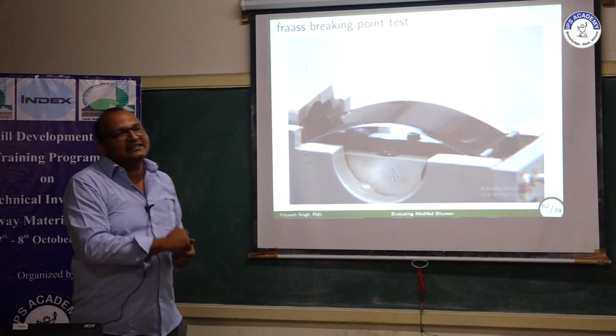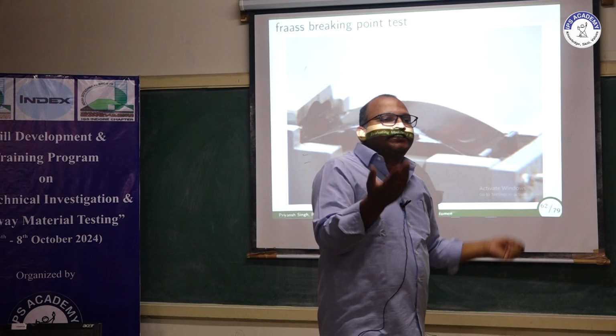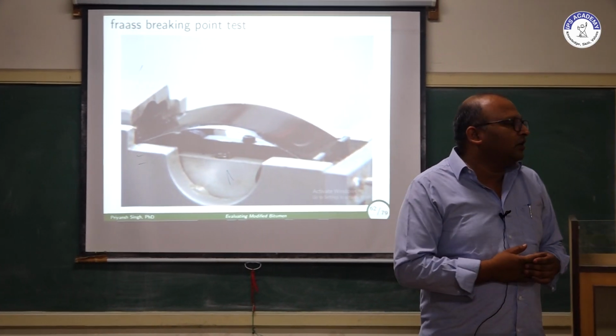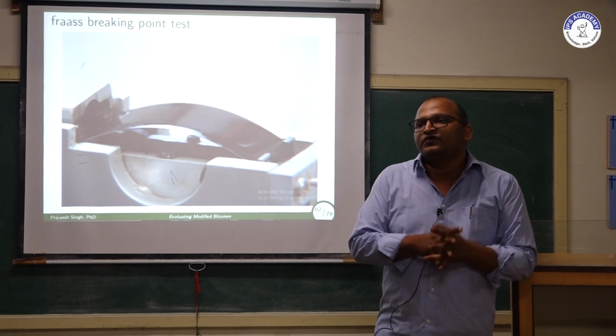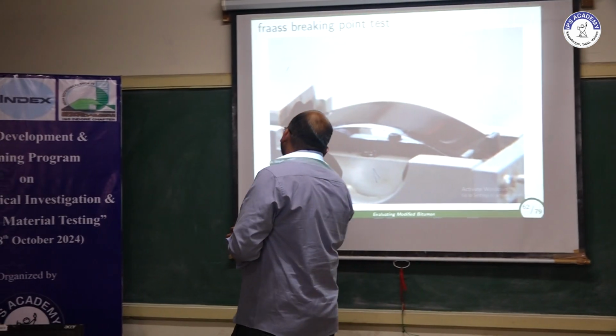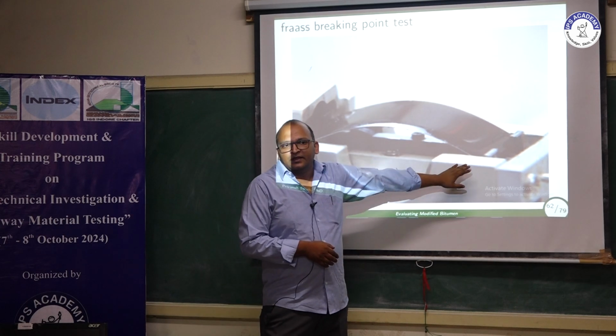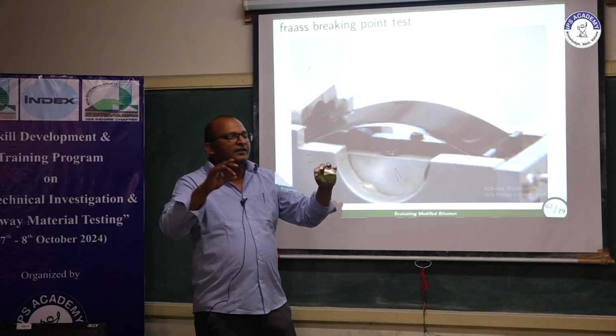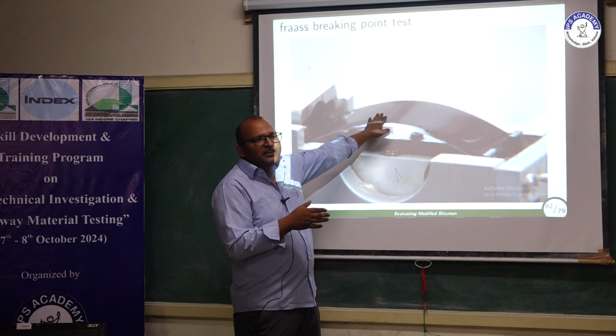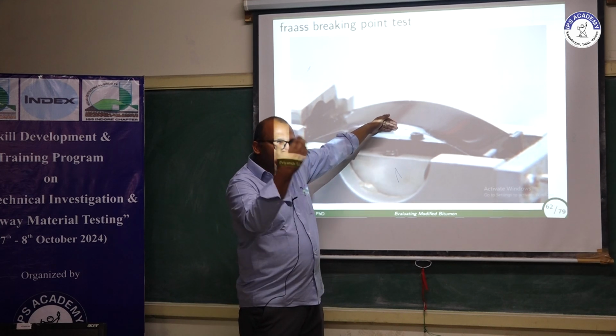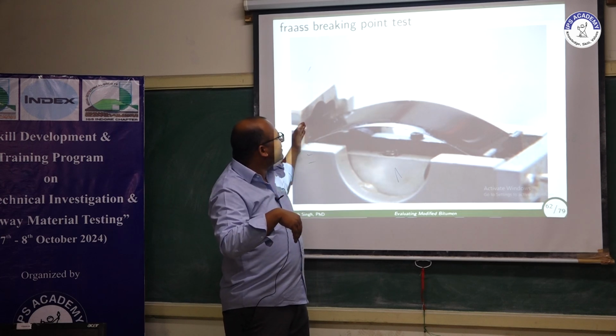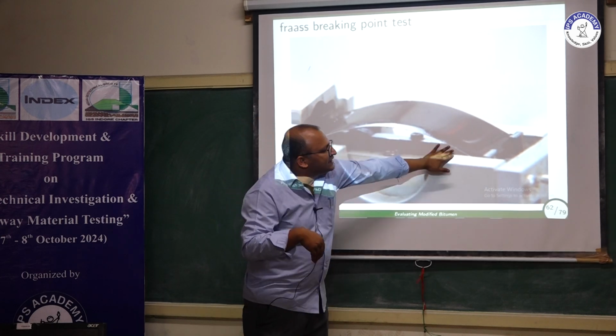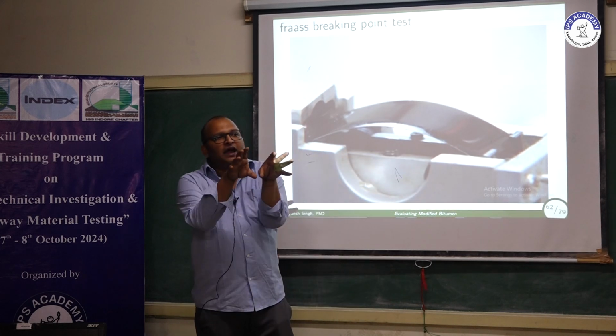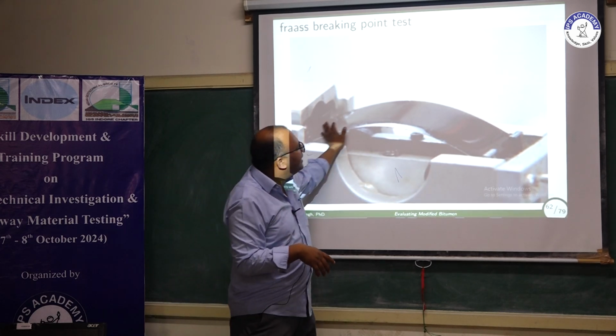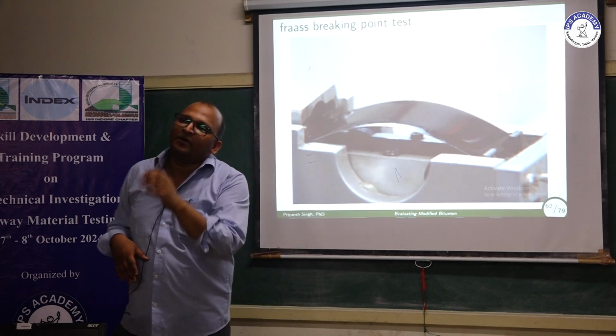The next test at 0 degrees Celsius, this is the only test. Now we have more sophisticated tests to characterize at 0 degrees Celsius, but we are not going to discuss that. This Fraass breaking point is a test which you can do to characterize binder at low temperature. So there is a small film. In the film you will coat your binder, and then you will decrease the temperature. Temperature may be 0 or minus, and after every 2 or 3 degrees Celsius decrease, you will try to press this so that this sheet becomes bent. Now whenever the binder attains a certain brittleness, due to this bending the binder will crack. The point where the binder cracks will be taken as the Fraass breaking point.